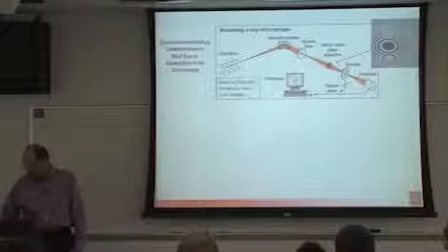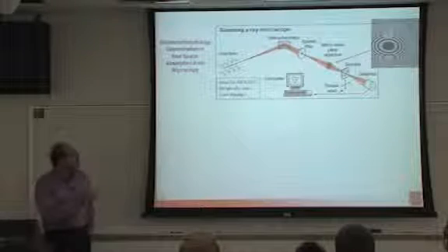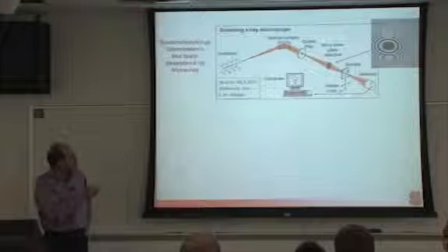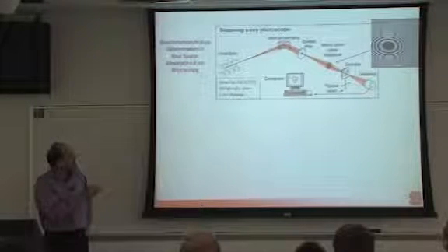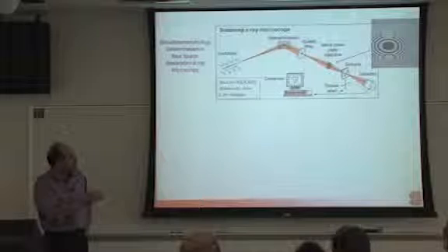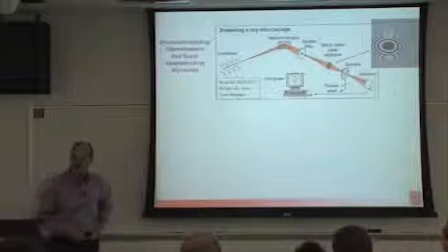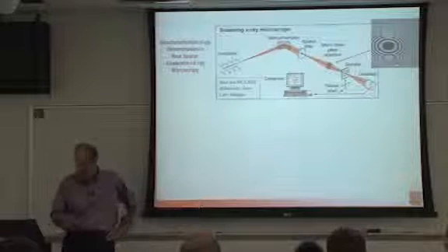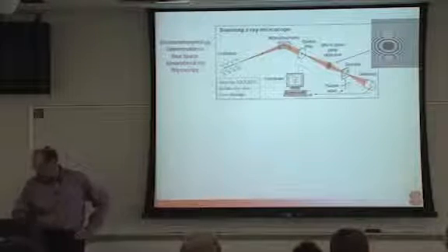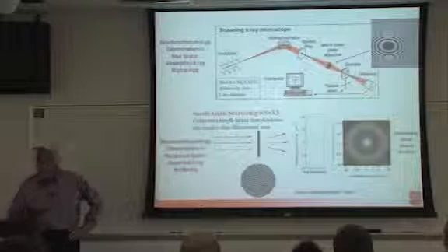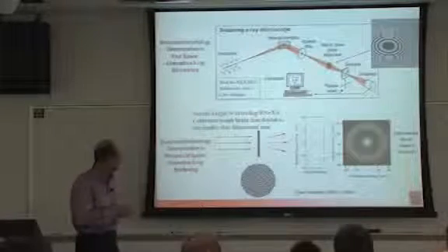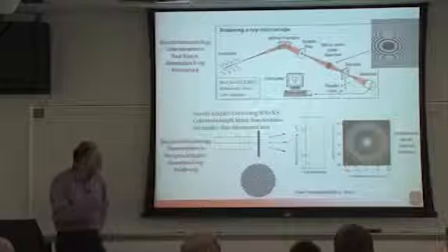So what do we have? We have two tools. A special light bulb. The light bulb is $100 million plus. Then it has a couple of beam lines, a monochromator. We have a zone plate to make a small spot. We can do microscopy. We can change this X-ray energy and therefore can do spectral microscopy. Spatial resolution is on the order of 50 nanometers. And then in order to go to higher spatial resolution, we do small angle scattering, but with soft X-rays.